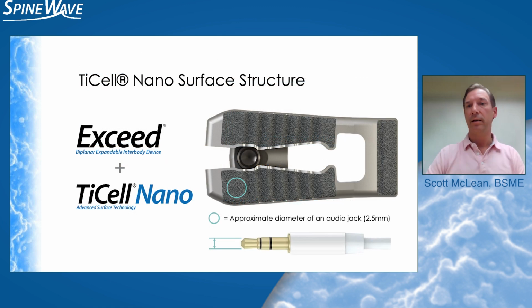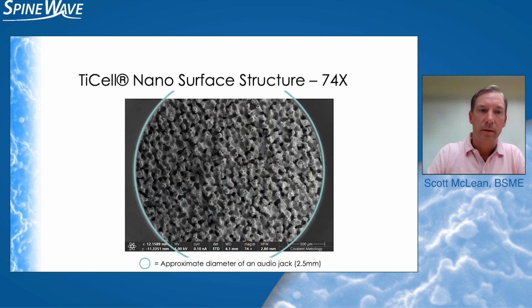So in order to give context to the surface and to the features involved, what we're showing here is the Exceed implant. This is a top view. So you're looking at the end plate contacting surface of the Exceed implant, and we'll talk much more about the Exceed implant later tonight. And that circle that's drawn on that surface is the approximate diameter of an audio jack that you would plug in on, say, an airplane. So we're going to take a look down the barrel of that circle, of that audio jack, and this is what you would see. You can see the rough textured surface, and this is what you see and feel on the implant surface.